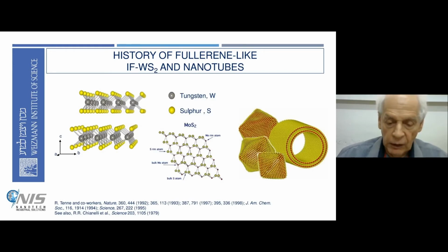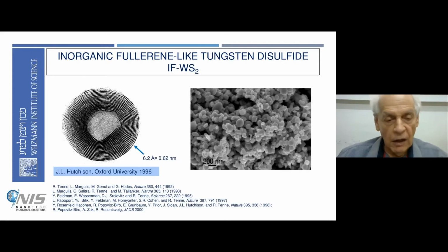This has been clearly indicated. You see now a TEM, transmission electron microscope picture, of such nanoparticles consisting of about 15 or 20 layers of tungsten disulfide. Each fringe is basically a 2D casting, a 2D reflection of a hollow closed structure of tungsten disulfide. If you tilt these nanoparticles in any direction, it will always look like that - a hollow closed structure made of several layers.